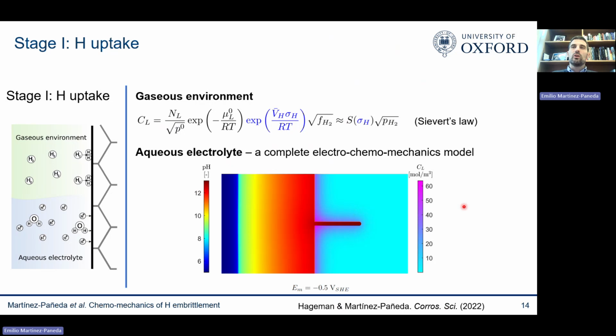We published this a few years ago for three main reasons. One is that it allows us to predict hydrogen embrittlement in aqueous electrolyte environment. So for example, relevant to that oil and gas failure that I showed you before, for a given environment, I can predict what is the uptake of hydrogen, and then I can predict how much hydrogen changes our mechanical and fracture properties.